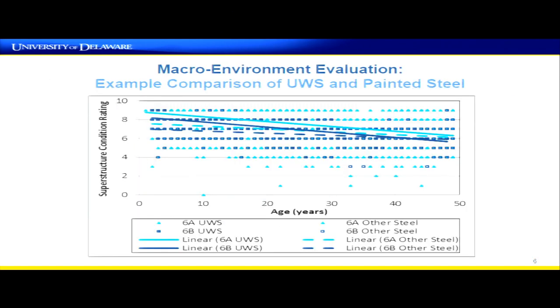Another way of looking at how weathering steel performs as a function of macro-environment is to compare it to painted steel structures. So again, this is high-level aggregate data from the NBI plotting the superstructure condition rating versus age, because we expect the rating is going to go down with age. We see there's a lot of scatter here, and every bridge that is weathering steel is a data point. Every bridge that is painted steel is a data point, and so you can't really see anything when you just look at this mess of 1,000 data points.